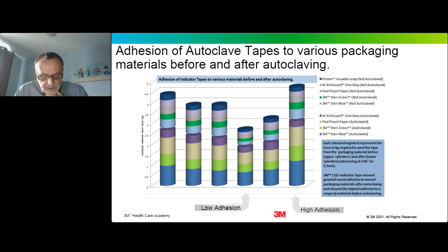It can also be seen that none of the tapes adhered particularly well to the reusable non-cotton-based material. And it should be noted that this had a very shiny surface. That's the very top blue bar on all of the columns. It's the Protex reusable wrap. So you can see that because they are very thin slices, the peel strength was relatively low. So the tapes were not sticking particularly well to that material. And as I say, this is because it had a very shiny surface, and so it was difficult for the tapes to grab onto that surface.